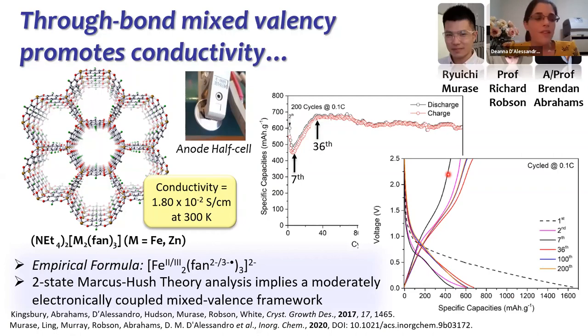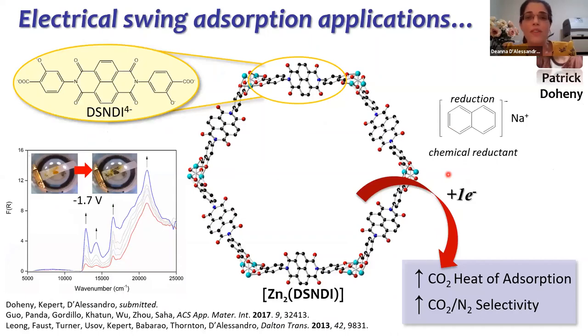The other application that I wanted to touch on very briefly, and I'm just showing one part here, is a framework that was first developed in a very elegant system from Saha's group, and we took great inspiration from this. This is actually an analog of the MOF-74 or CPO structures that many of us know well. It is also based on an electroactive naphthalene diimide ligand, which, using our solid state spectroelectrochemistry, we can demonstrate can be reduced by one and two electrons, and we can also do this chemically. If we do that, we find that the heats of adsorption and even the selectivity of particular gas molecules, in this case carbon dioxide over nitrogen, increase when we start playing around with the charge state of the framework.